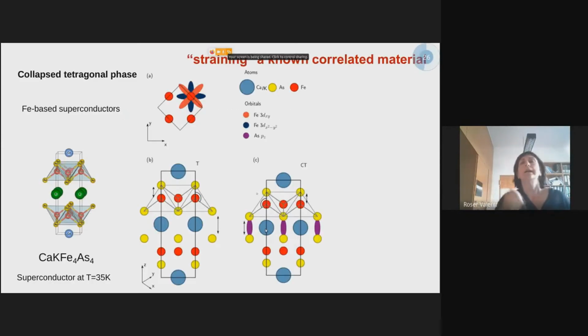With that, I would like to show you an example of straining one of these high TC iron-based superconductors, where, in fact, by doing simulations, we found out that one could have very interesting properties that could even functionalize the system. So let me show you what we have been using for these materials. So this is calcium, potassium, iron 4, arsenic 4. Again, this is a family member of the iron-based superconductors. The system is a paramagnetic metal. When you go down in temperature, it becomes superconducting at 35 Kelvin. What is interesting is that the structure of the system is tetragonal, and what is special about this tetragonal structure is this body centering, so that you see these planes of iron arsenic basically separated by these cations, potassium and calcium.